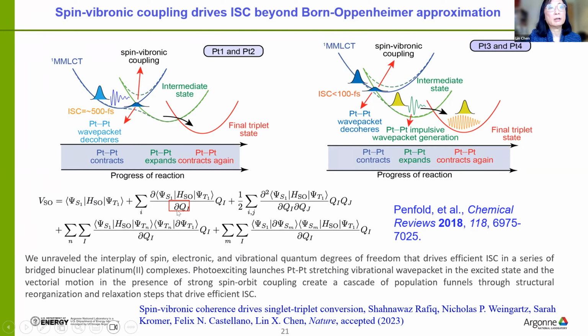In particular, in this case, when the initial state is close to a conical intersection, the vibrational motion enables the crossing of these two states, and that actually breaks the Born-Oppenheimer approximation limit. In that case, the vibrational motion at this point becomes vectorial instead of oscillation around the equilibrium position. So basically, that's what we learned, and we started from the APS.